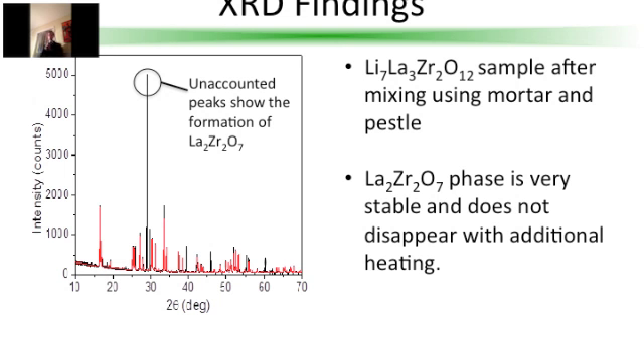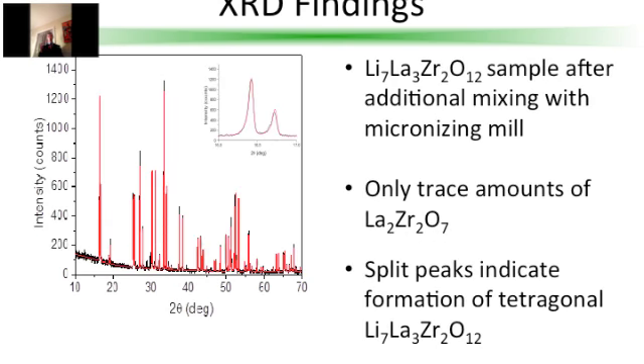Now, because I wanted to make phase pure samples, I needed to find a way to remove this lanthanum zirconate oxide phase. So, to actually prevent the formation of this phase, I started to use a micronizing mill in addition to mixing the samples with a mortar and pestle. Now, the results shown here came out a bit better than last time. As you can see, the fitted model matches very well with the experimental data. There's only one problem. The double splitting in the X-ray diffraction pattern, which you can see in the upper right hand corner, that's just a magnification of one of the peaks which has the double splitting, indicates that I formed the tetragonal phase of lithium lanthanum zirconate.